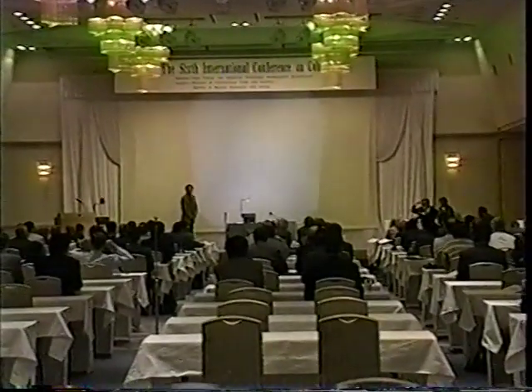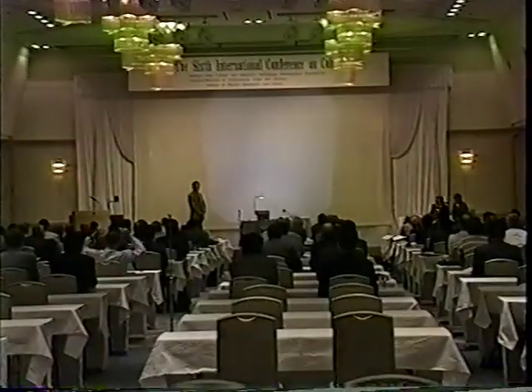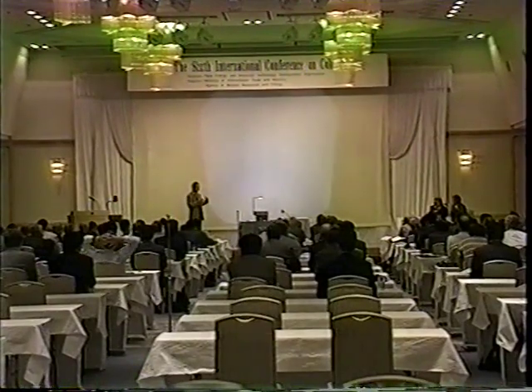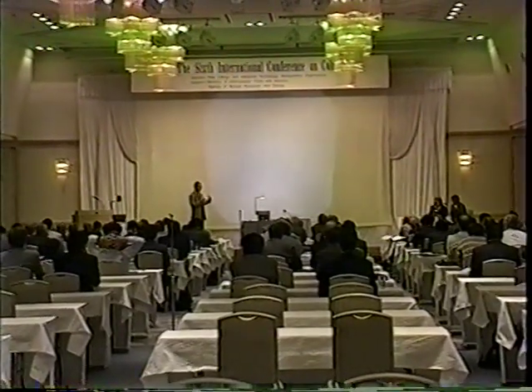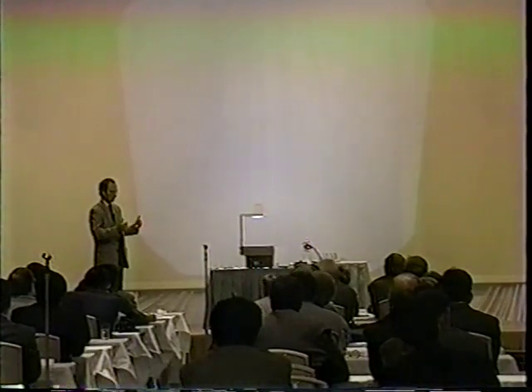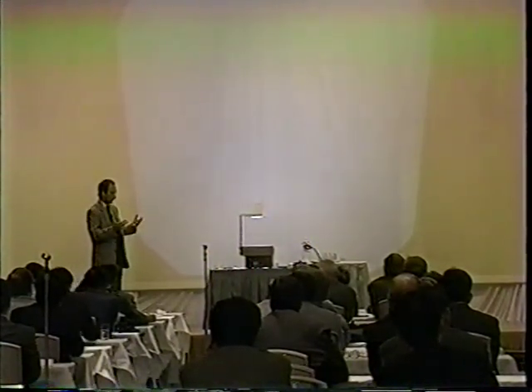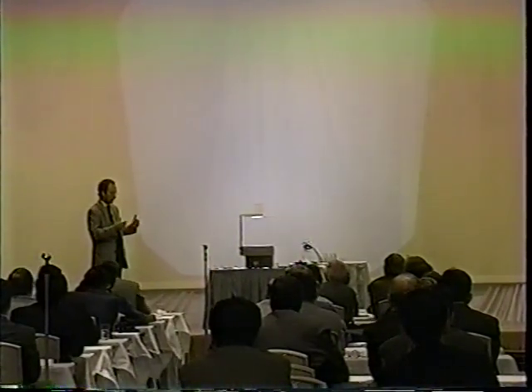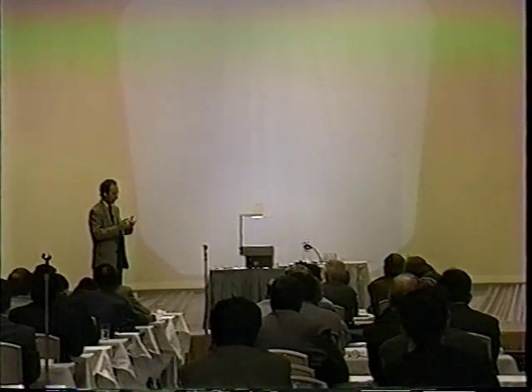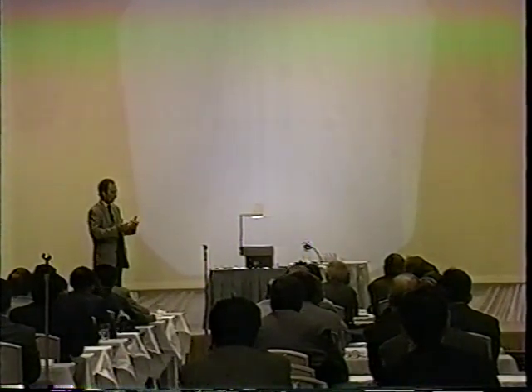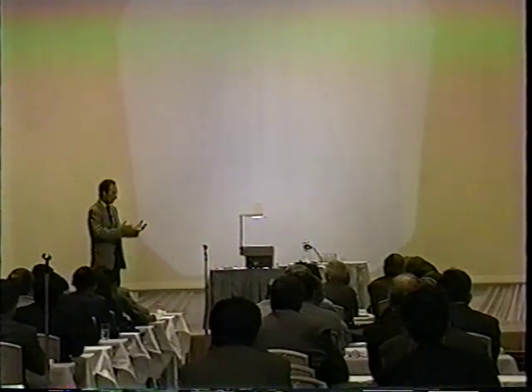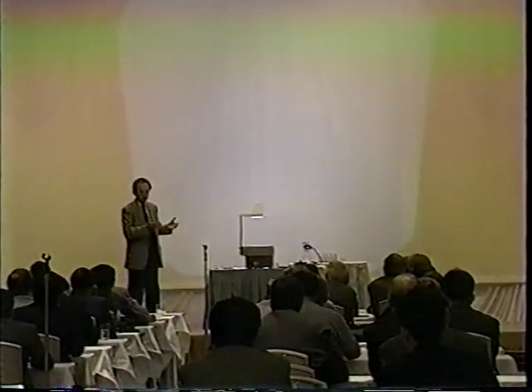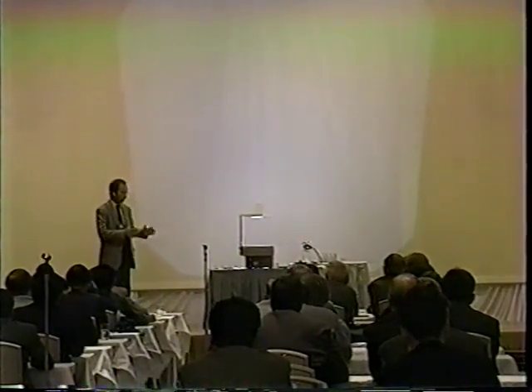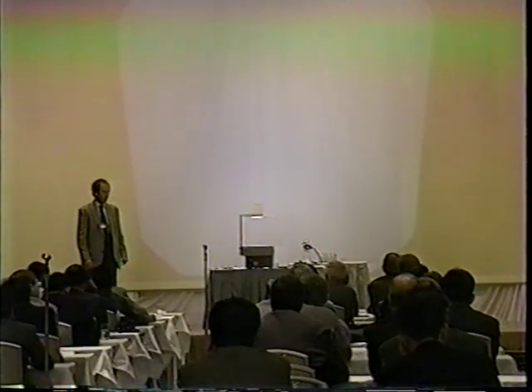Well, our feeling is that if we have oriented dislocations, maybe they help the material to relax the stress. But you know that when you introduce hydrogen, there is a formation of dislocations, random formation of dislocations, and this formation produces crossed dislocations that can reduce the ability of the material to relax the stress. In terms of help for the mass transfer, probably the effect is negligible, but this is just a feeling. A lot of work is required in this field if we want to know everything. Thank you.